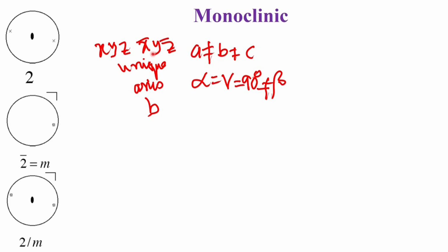So, overall the volume of the unit cell, we have not defined that yet. The volume of the unit cell will be defined now. Of course, there are two possibilities for the unit cell, so let us first define the unit cell possibilities. The unit cells can be a primitive lattice as well as a C centered lattice. So, the space group can be P2 as well as C2.